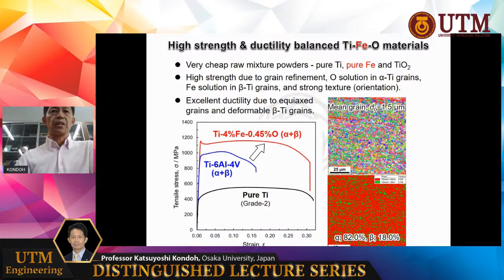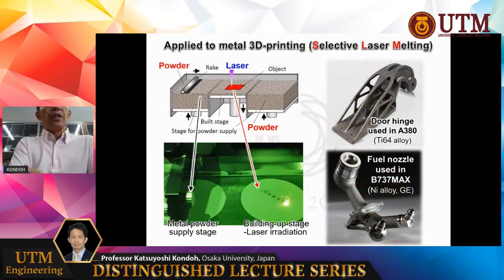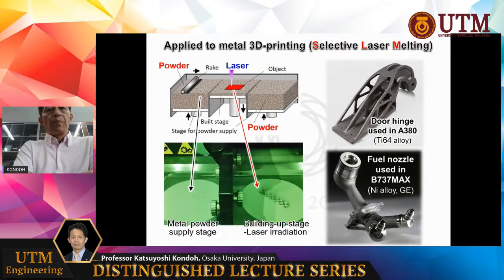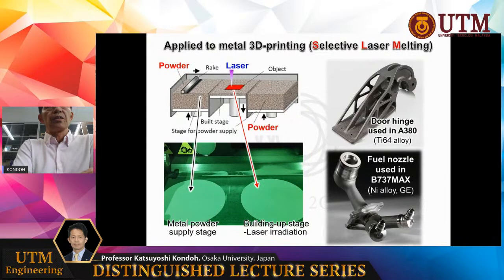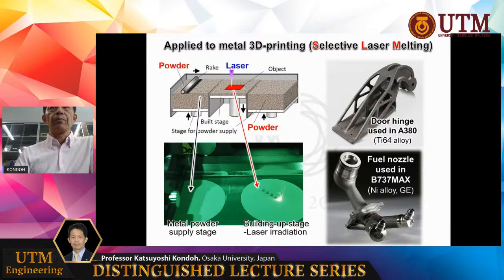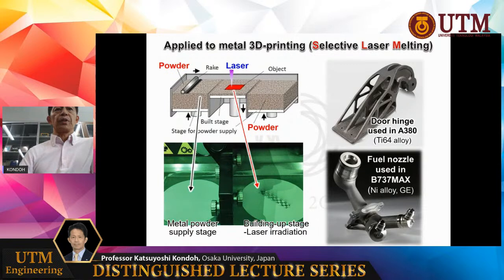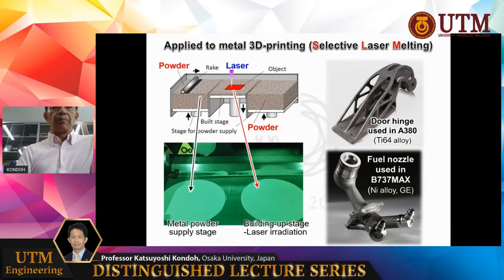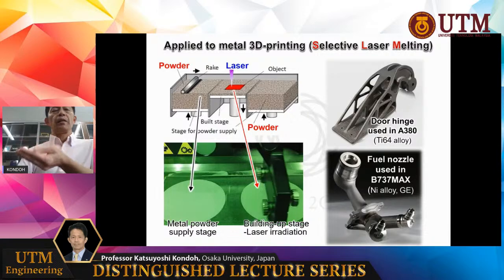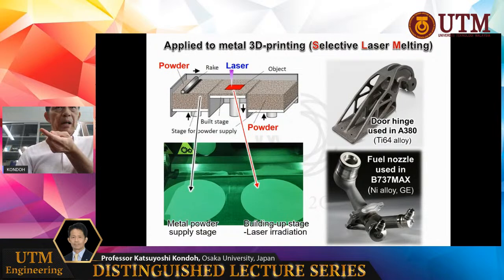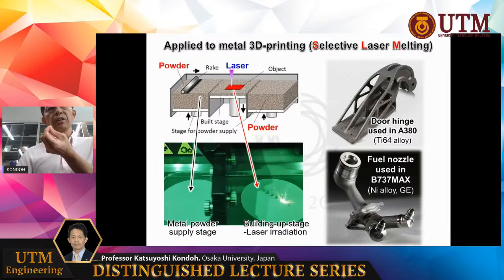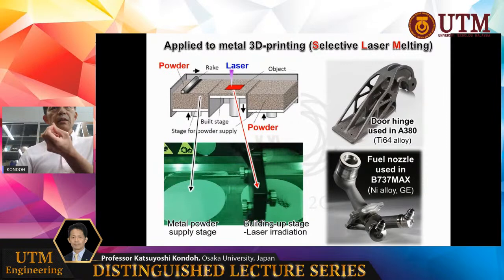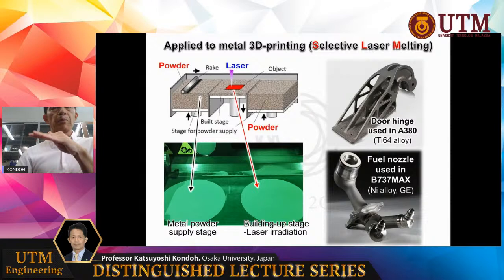So based on these results, we apply this material design to metal 3D printing. In that case, we use the selective laser melting process, which we call the SLM process. This is a well-known process: powder is spread on the building stage and a laser is applied to the metal powders. By irradiation, the powder melts, and the melted powders completely combine and quickly solidify. Layer by layer, we finally obtain the three-dimensional parts.